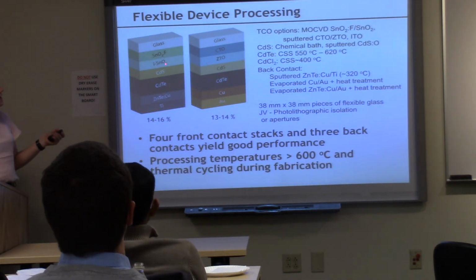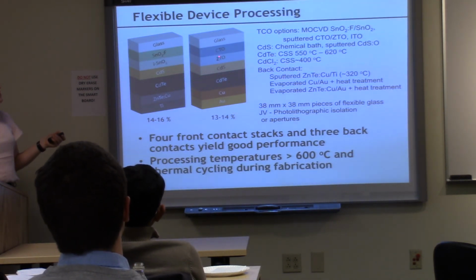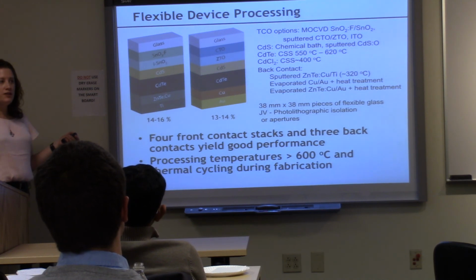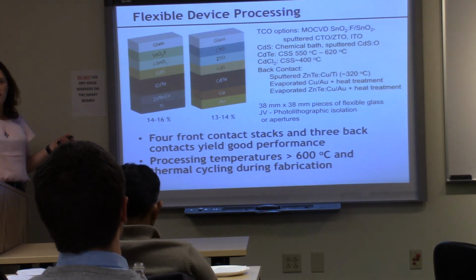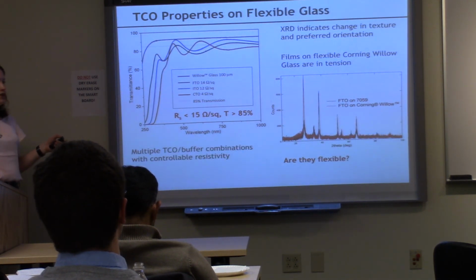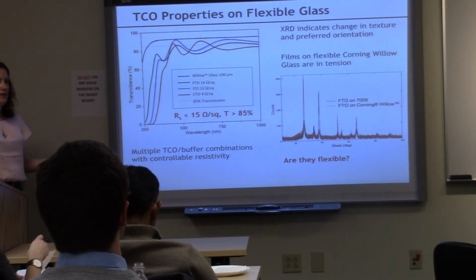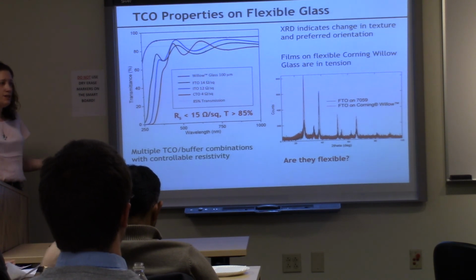So we looked at, the first barrier we had is to look at these contact materials here. There's a lot of work that goes into making these flexible because they're used in the display industry and everybody wants a flexible display. And the urban legend around them is that transparent conducting oxides are inherently brittle and that you cannot bend them. So we started this project, we wanted to first make sure we could make good TCOs on Willow, because if we can't make a cadmium telluride device, we may as well just stop. And then could we bend them, because these things could be deal breakers.